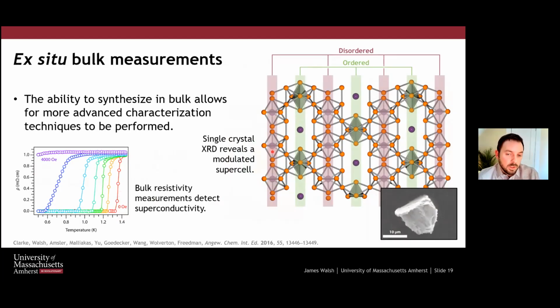Because we can grow single crystals, this is a single crystal recovered from the large volume press reactions, around 10 microns. That's big enough, even with laboratory sources, to be able to do X-ray diffraction. When we do this, we find it's even more complex than we thought. So I said on the previous slide that the copper bismuth system is remarkably complex. It's even more complex than that because it's a modulated supercell. It's a modulated structure. And so what I'm showing here is the modulated supercell.